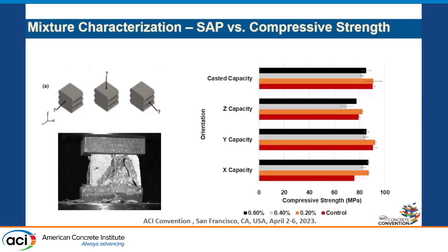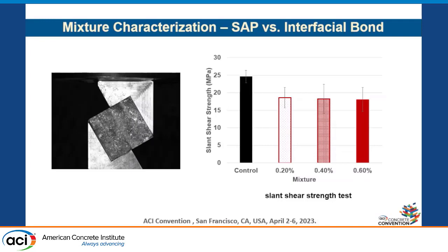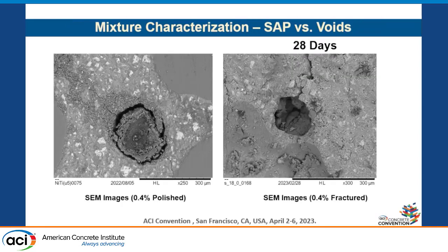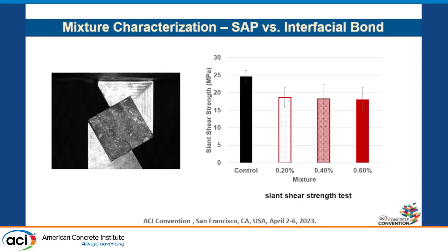But the rest, for example, about compressive strength, you will see that the printed concrete goes as high as 75 to 80 megapascal, and that shows how robust our mixture is. So we don't have any problem with that. And also about the shear, we use the slant shear strength to represent the interlayer bond. And this is actually a very effective method. And as you will see, we have lower interlayer bonds in our samples, which is technically because of the voids that SAP produces upon the release of water, of course, at later ages. My previous results on SAP show that over time, these voids will be filled, and it's not that effective. But anyway, what you see here is about 28 days. So we have a reduction in interlayer bond, and that is also something we need to look at.